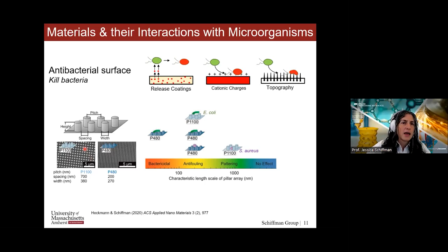And what we show here is this P1100, which means that our pitch, or our center to center distance between two different pillars, is about 1,100 nanometers or about 1 micron. In this P480, we have a smaller pitch. So this means that our pillars are closer together. We thought that this pitch distance is the characteristic length scale. And that's what we have plotted over here. This is a heat map, or just a summary of the data that we saw.